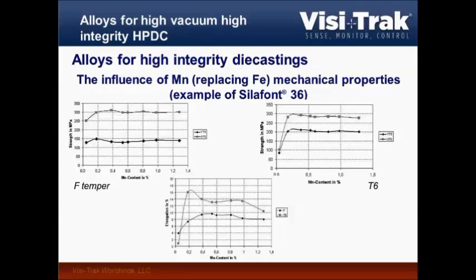And lately Ray Donoghue from Mercury Marine said, well, actually the ideal point would be a 0.3% manganese content. This is where we usually see the peak in properties. Plus 0.3 is even better than 0.4, 0.5 in terms of sludge particle formation. But at that level, even with a 0.25 iron, an additional mechanism is needed to beat the die soldering, and therefore Mercury Marine has added the strontium, which was proven to help reduce the die soldering.